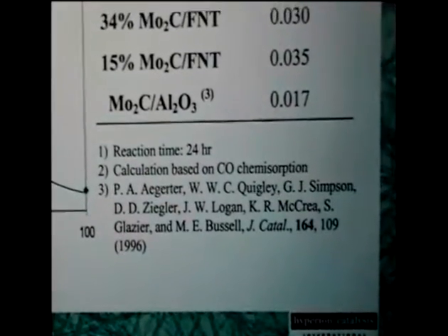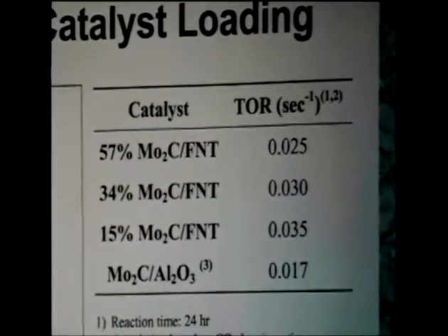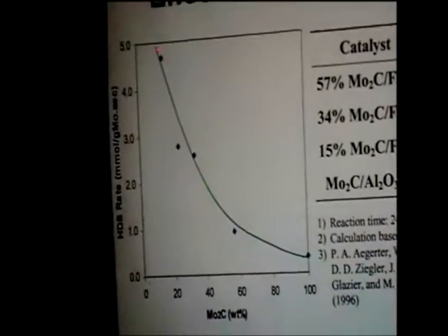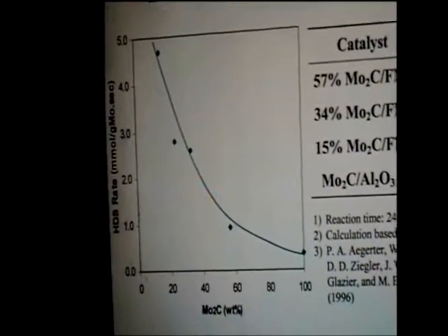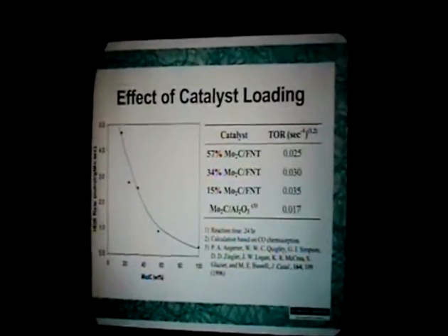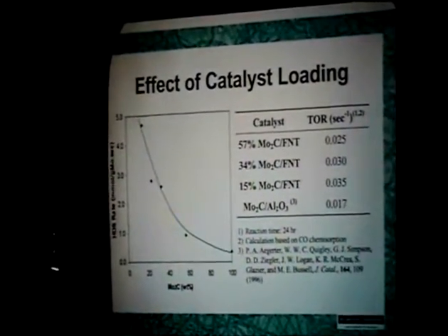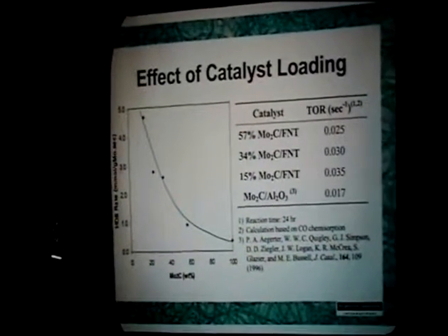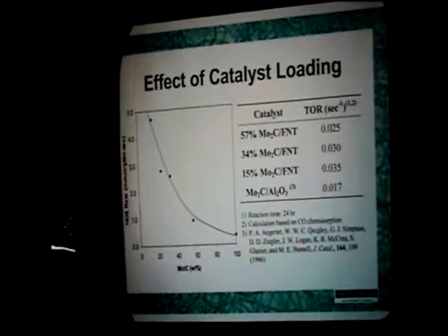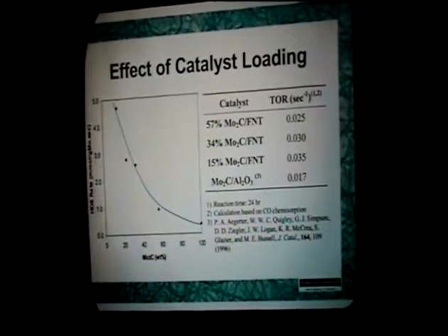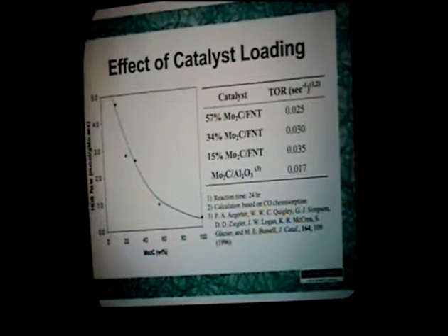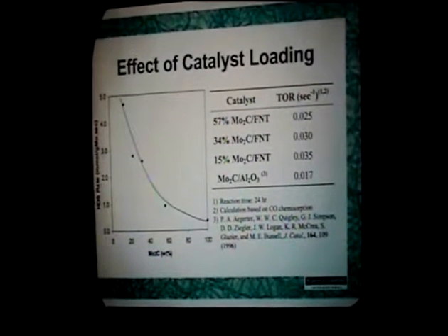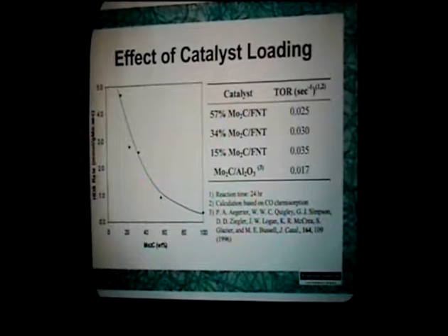Here's again the HDS rate as a function of molybdenum carbide. Then here per gram, and here you see an effect of again loading, increasing the number of sites versus decreasing the surface area. But if you use, for example, CO absorption to count how much molybdenum carbide you have on the surface, they are not very much different. There is some difference, not much, but also it compares very well with the literature values of the same reaction. So I think we understand the chemistry well. It's just a question of a better material, or how to make or support this material.